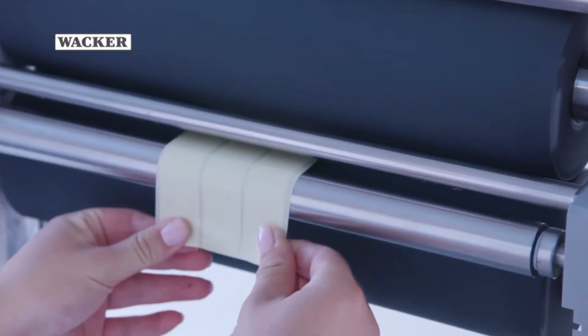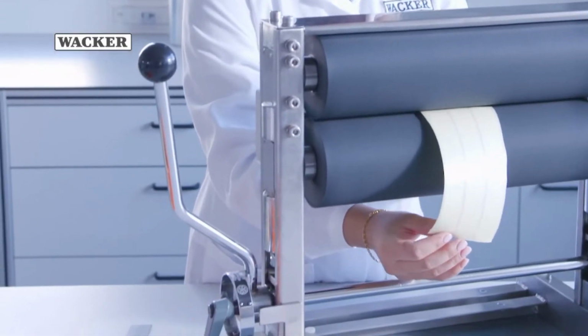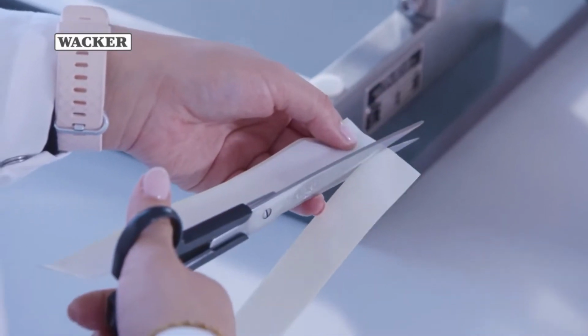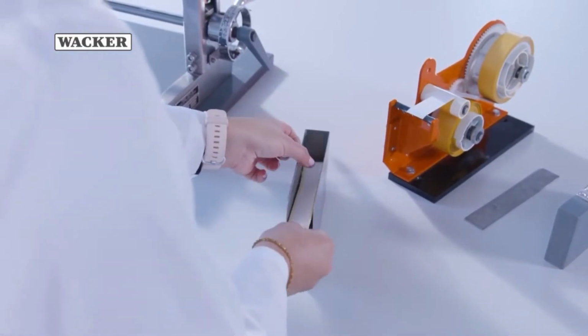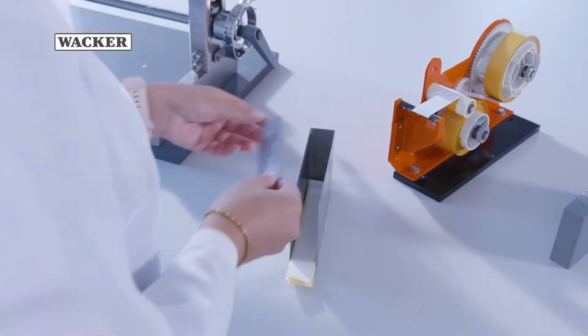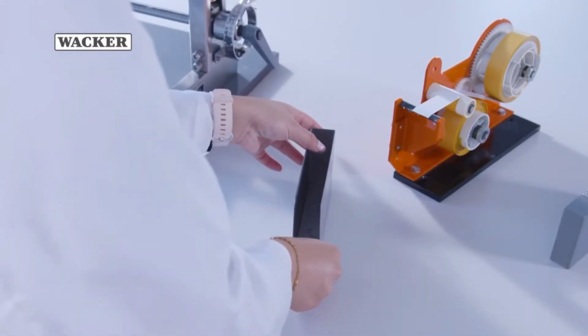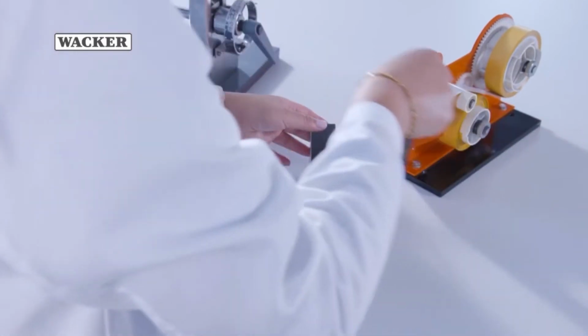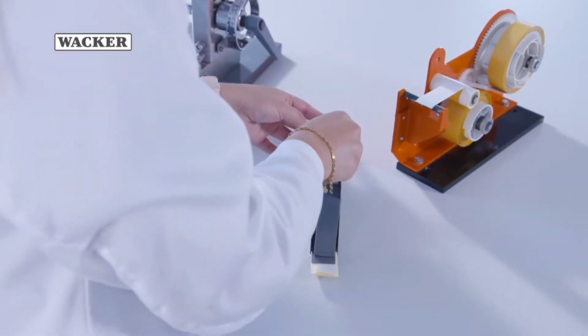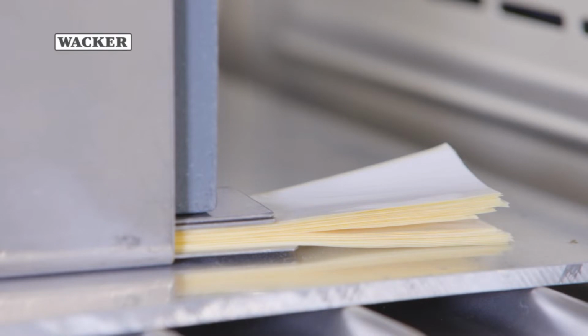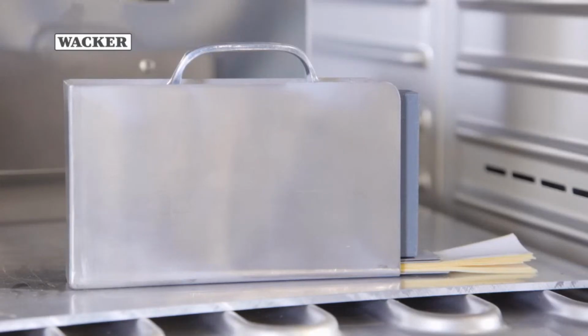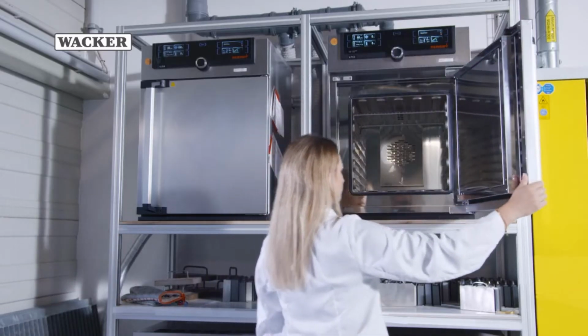To ensure the silicone coatings are always of optimum quality, Wacker tests every step of the manufacturing process in the lab. Various adhesive tapes or labels are stuck onto the backing material coated with the target coating weight, relaminated, and test strips are cut out of the backing. The test strips are stored for 20 hours at a temperature of approximately 23 degrees Celsius between 2 flat metal plates or glass panes under a pressure of 6.87 kPa, 70 grams per centimeter squared.